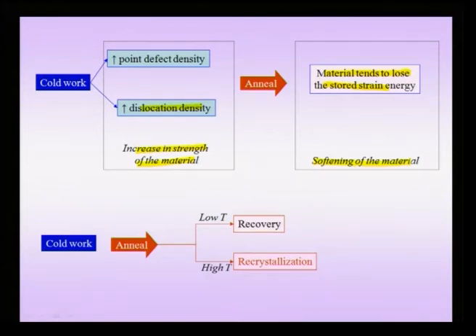This annealing itself can be done under two circumstances. We can do an annealing at slightly lower temperatures, or we can do it at higher temperatures. At lower temperatures, of course, we are supplying less activation energy, and the processes which take place are collectively called recovery. And at higher temperatures, we have the phenomenon of recrystallization, and we will try to understand these technical terms in a little more detail in the coming slides. So, we have a cold worked material which has been plastically deformed, for instance by rolling, forging, extrusion, etc.